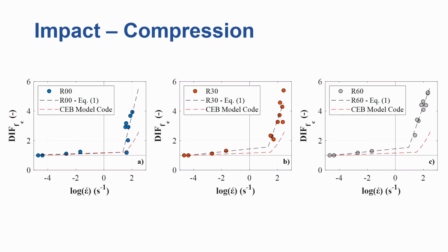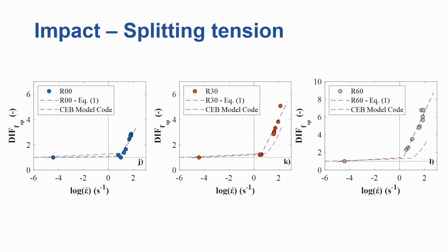What's more interesting is I'm plotting in the red lines the predictions by the CEB Model Code 2010, and as the rubber content in the concrete increases, the expressions kind of become inappropriate for rubberized concrete. We see that under compression, and the same here for splitting tension. And we just see that the rubber really dominates or controls the behavior under impact.